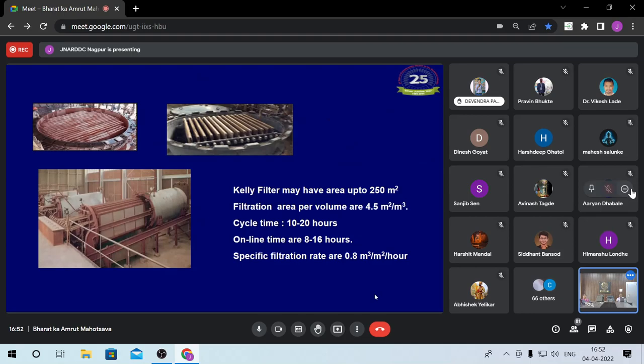I will show you how this looks. The entire plate and frame type of system is there. The aluminate liquor flows through it. These Kelly filters have a very high area of 250 square meters. The filtration area per unit volume is around 4.5 square meters per cubic meter. The cycle time is 10 to 20 hours and the on time is 8 to 16. And you attain a specific filtration rate of around 0.8 cubic meters per square meter per hour.